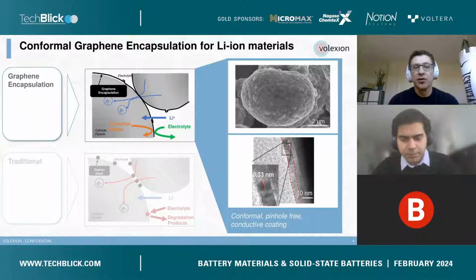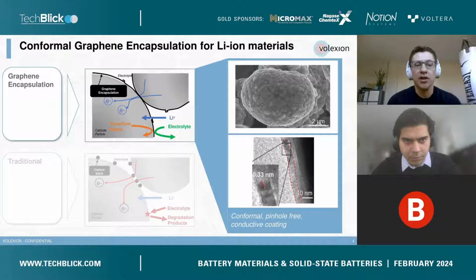So the resulting configuration can be seen on the top left schematic, where you have this nanoscale carbon-based, graphene-based coating that is engineered in a way that lithium ion can freely diffuse through the coating, while creating a completely isolating barrier that prevents the electrolyte from accessing the surface of the cathode material and prevents the transition metal from leaching out of the cathode material, because then they create cascading and crosstalk effects throughout the battery that are detrimental to the performance.